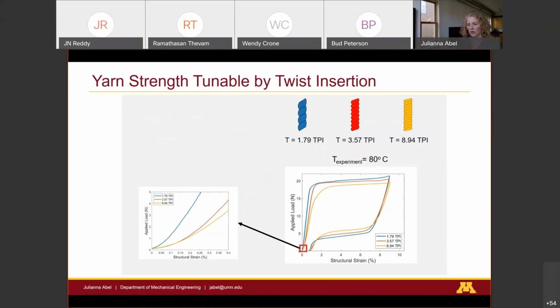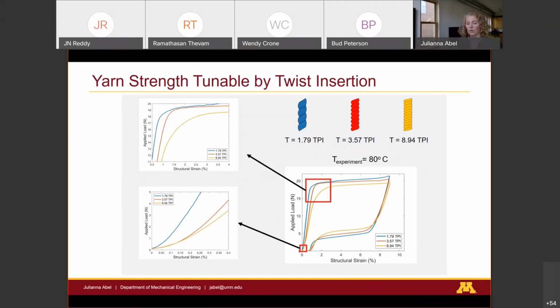With more twist, we're also seeing this varied recruitment into the structure. And we're seeing these interesting regions where we're transforming over a larger range. So when we're going from austenite to stress-induced martensite, instead of having a very sharp transition that we see in parallel fibers, we're seeing this gradual transition that could actually be useful for some applications. And we're seeing this reduced hysteresis band.